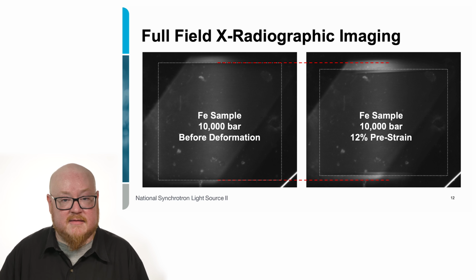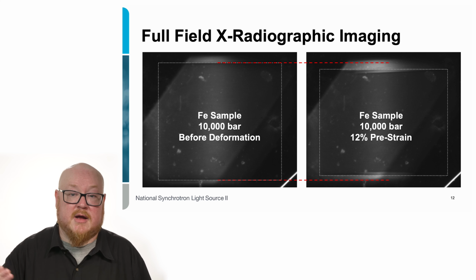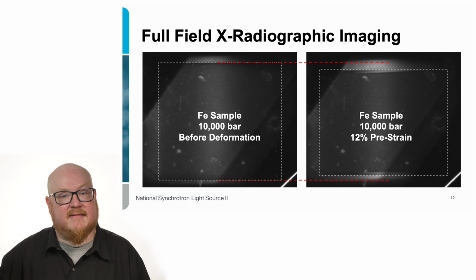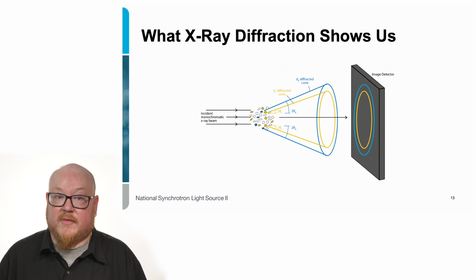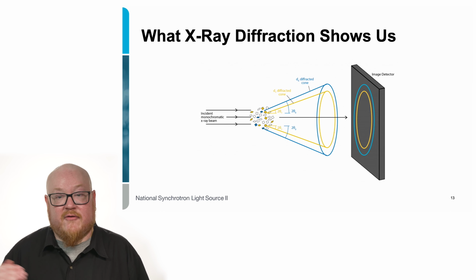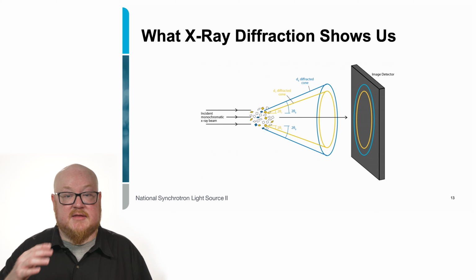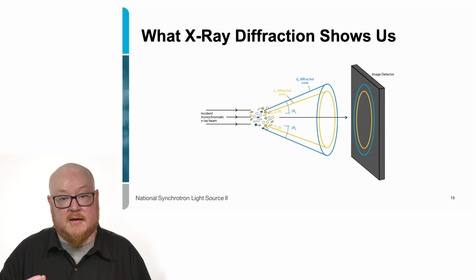And you can see clearly that the sample has changed its length. And this is what we measure in order to be able to determine what next steps to take during the experiment. Now, to talk a little bit about the X-ray diffraction, what the X-ray diffraction shows us is the different crystals that are in the iron sample at high pressure.